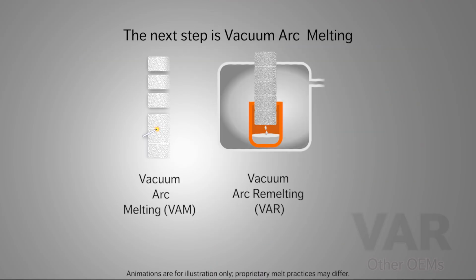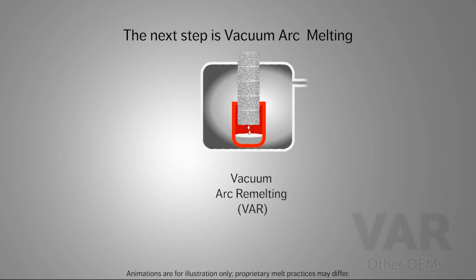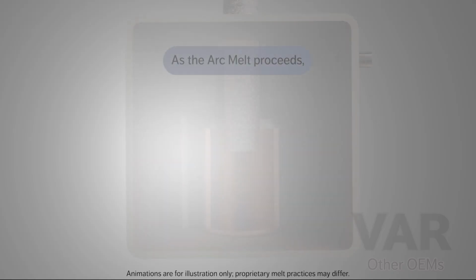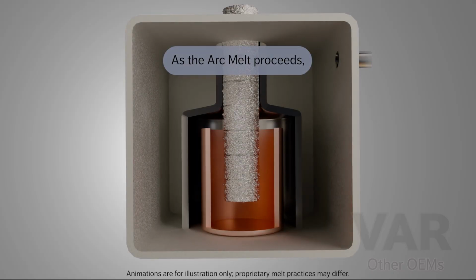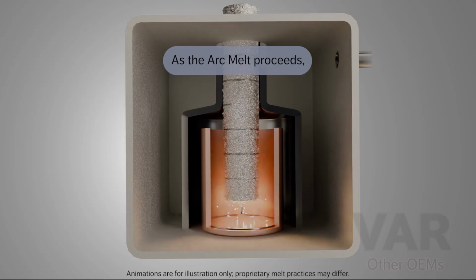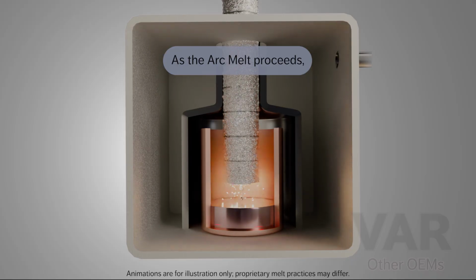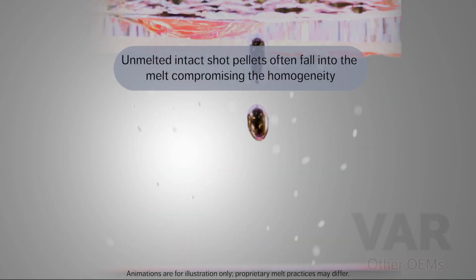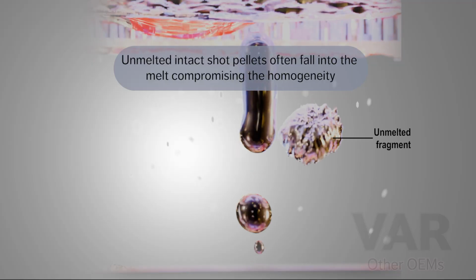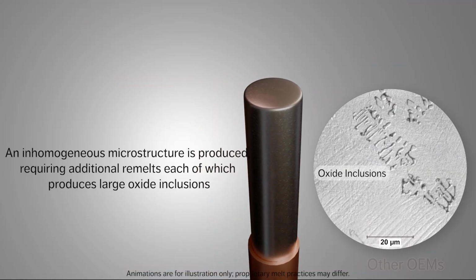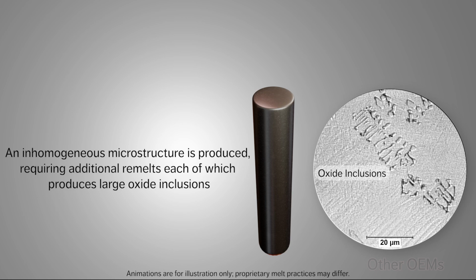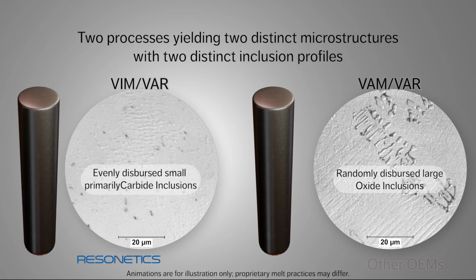The next step in VAM-VAR is vacuum arc melting, VAM. As the arc melt proceeds, unmelted nickel or titanium shot often fall into the melt, compromising the homogeneity of the resulting microstructural matrix. An inhomogeneous microstructure is produced, requiring additional remelts, each of which produces predominantly oxide inclusions that are usually larger than carbide inclusions. Two processes yielding two distinct microstructures with two distinct inclusion profiles.